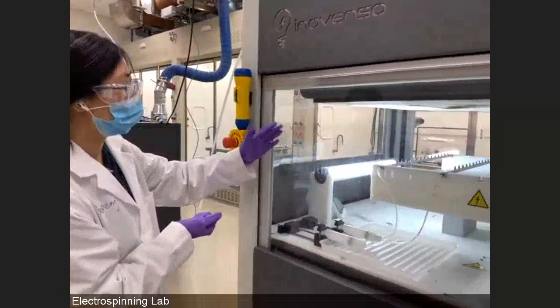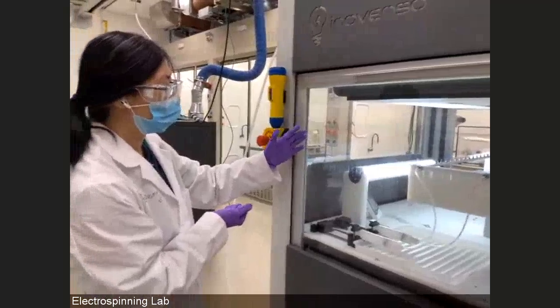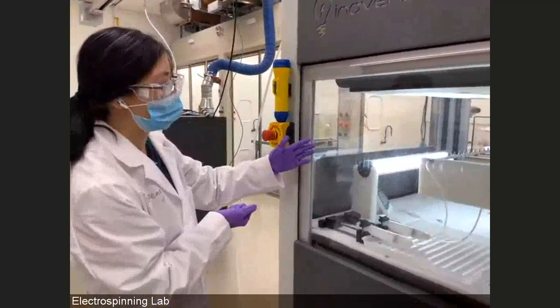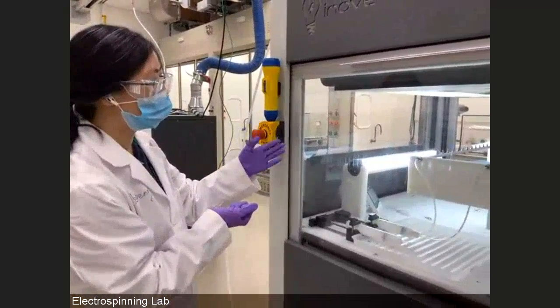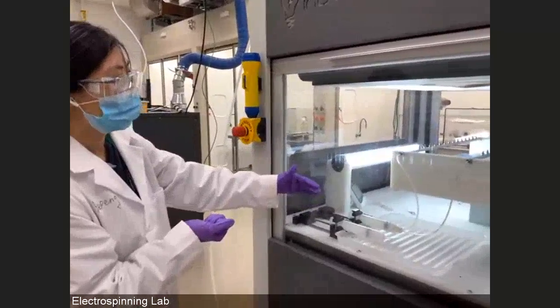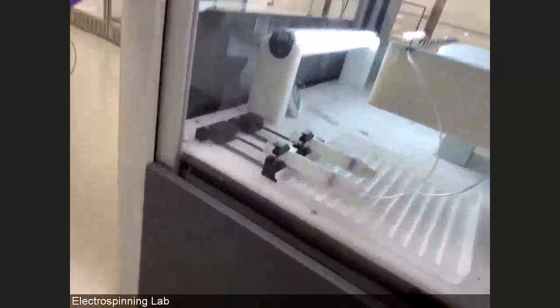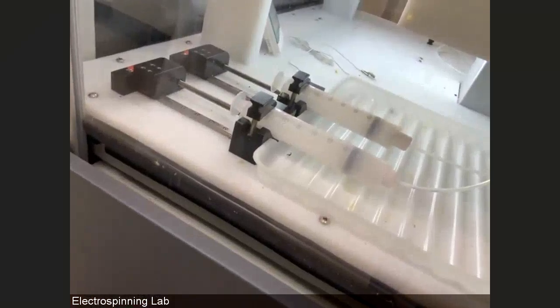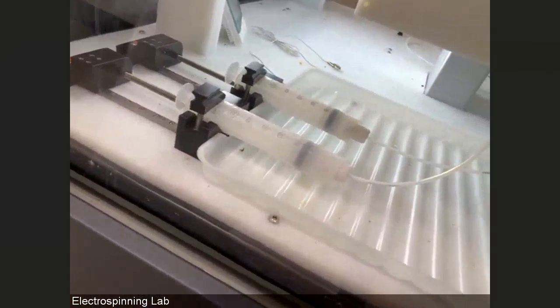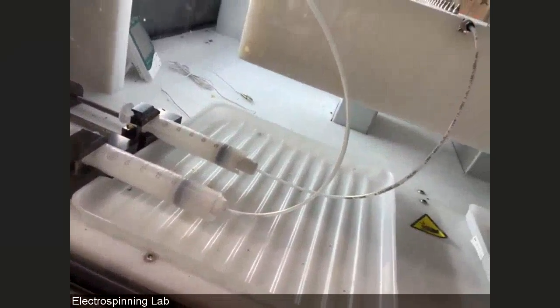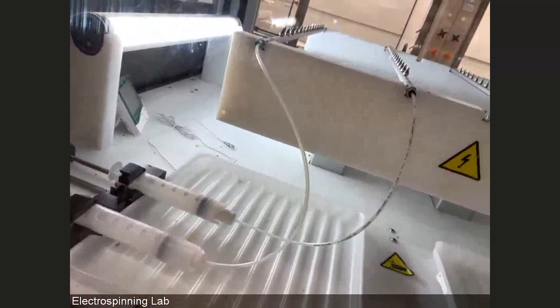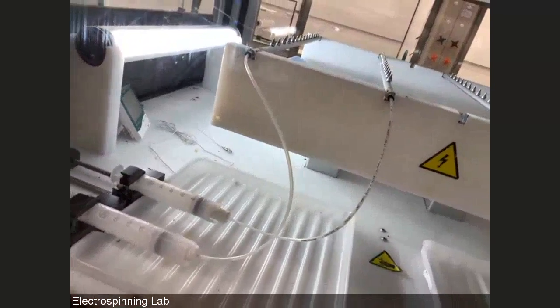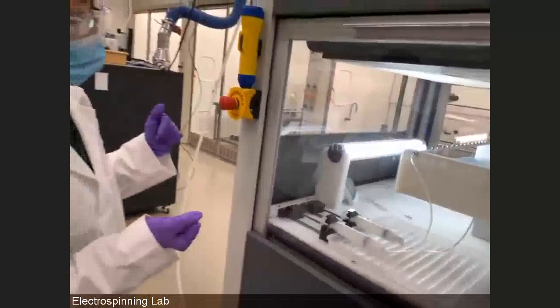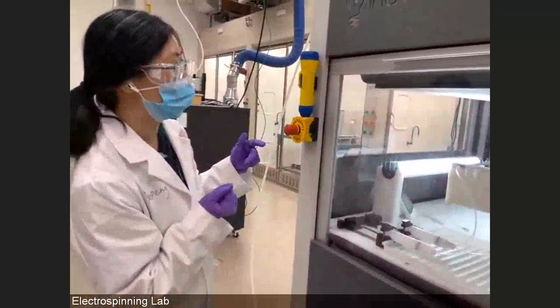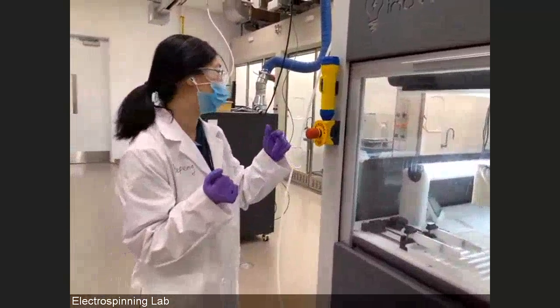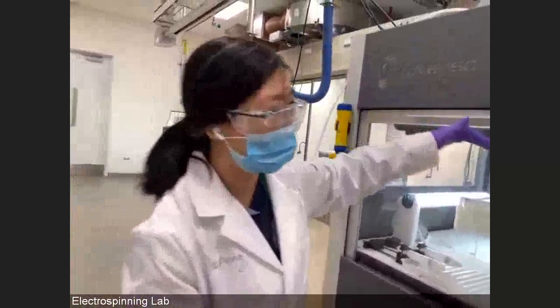The advantage of that is you can troubleshoot individual nozzles if there's a problem, and also you can introduce different materials to different syringes to generate a heterogeneous structure in your final sample. With this setup, we can deposit on a web 0.5 meter wide and 30 meters long. The cool part of this machine is that we have the roll-to-roll setup for the web.